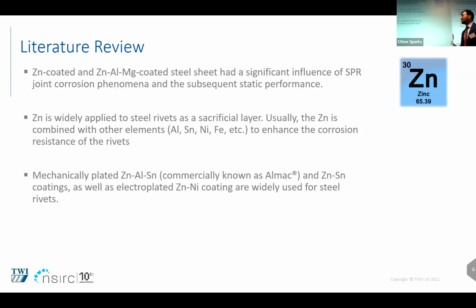So zinc is combined with other elements like aluminum, tin, nickel, iron, etc., to enhance the corrosion resistance of rivets, and they are mostly used for similar or dissimilar metallic materials. Right now, the commercially available, widely used and widely accepted coating is zinc, aluminum, tin, which is known as Almac coated rivets, and zinc tin coating. They are the most widely used rivets in multi-material construction for joining aluminum sheets of different thickness, as well as aluminum and sometimes steels. And the other one is zinc nickel coating that is used for steel rivets, but not that much.